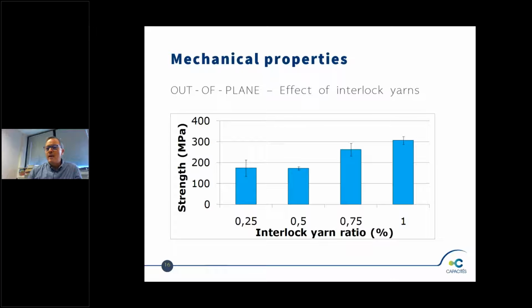keep a quite high level of stress above 300 with 1% of yarns, which is quite satisfactory, because with no yarns, we would be far below 200 megapascal, which means that we reduce the strength of the specimen by something like 30 to 50%, just because it's a laminate, and the criterion for the failure is not the same anymore, because you will have a delamination between the plies.